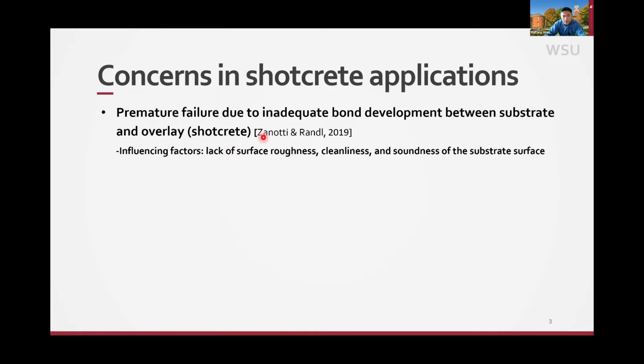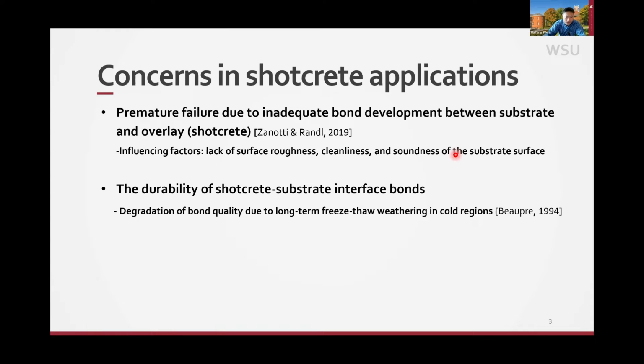The factors that can affect the bond between the two layers of material can be roughness, whether it is smooth or rough, whether it is clean or there's debris, or even the curing compound. Or whether the existing underneath material is in good shape or has been deteriorated. So those all can affect the bond performance. And the other performance concern can be related to freeze-thaw, especially in the cold area. The freeze-thaw may affect the bond performance in the long term.